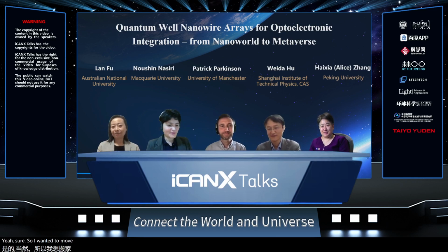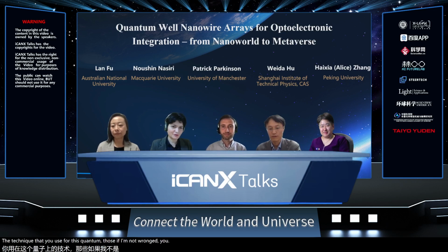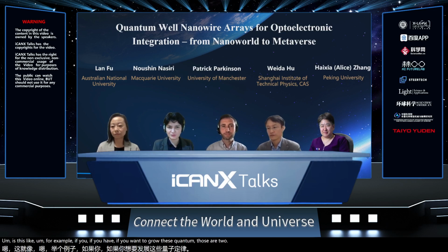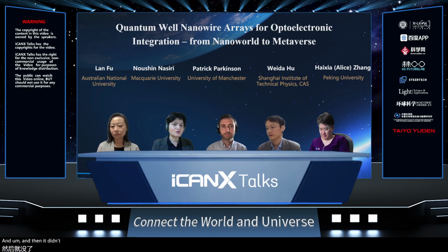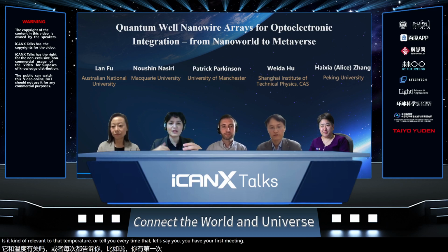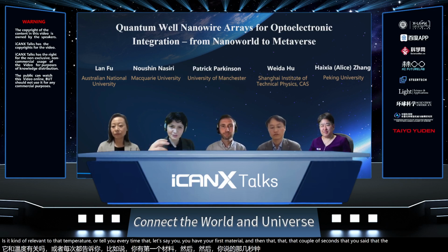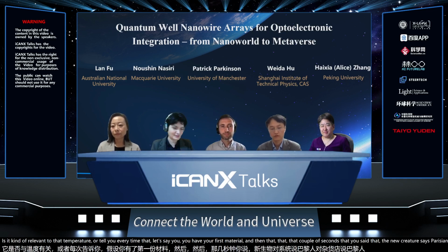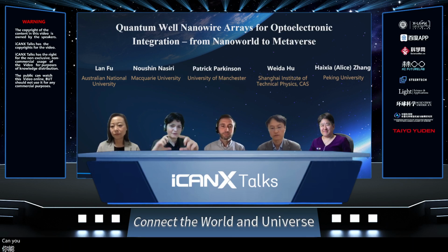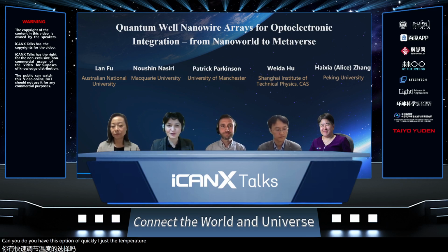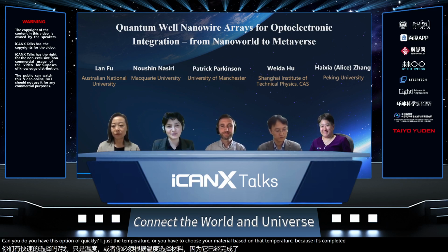So I wanted to go back to the technique that you use for these quantum wells. If I'm not wrong, you mentioned that you use a temperature around 700. If you want to grow these quantum wells, there are two different materials. So when you are selecting these two different materials, is it relevant to that temperature? Every time, let's say you have your first material, and then in that couple of seconds you said the new precursor is purged into the system to grow the second, the small bandgap material, do you have the option of quickly adjusting the temperature, or you have to choose your material based on that temperature because the temperature cannot be adjusted very frequently?